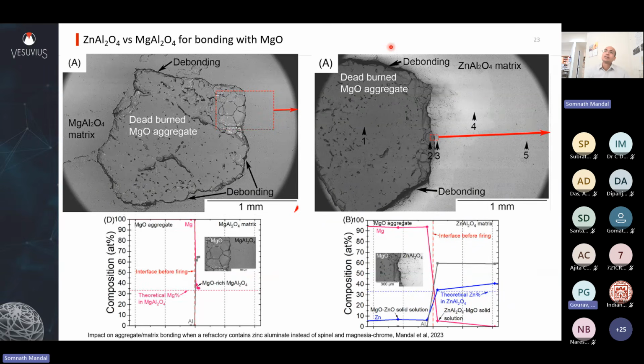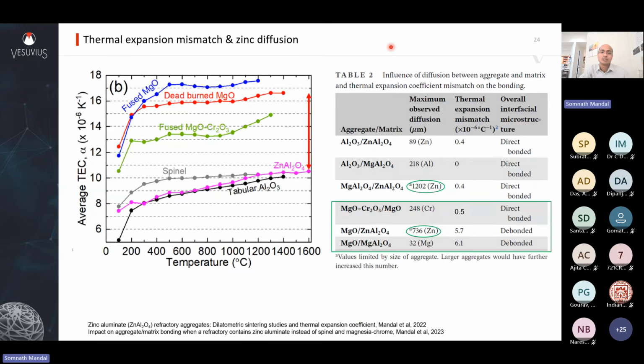In your magchrome brick, you have a lot of magnesia aggregates, and then you have chromite and magchrome co-fused or co-sintered grains. Let me show you this curve. The reason you have high thermal shock resistance in magchrome brick is that you have high-expansion fused or sintered magnesia, and then you have magchrome fused aggregates, and MgCr2O4 will be somewhere around here. Due to this delta in the thermal expansion coefficient, you have a little bit of debonding and microcracking that gives you thermal shock resistance.